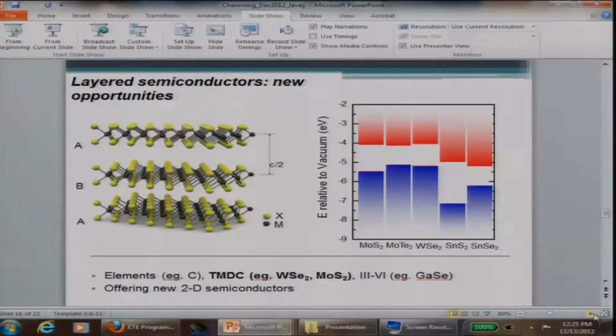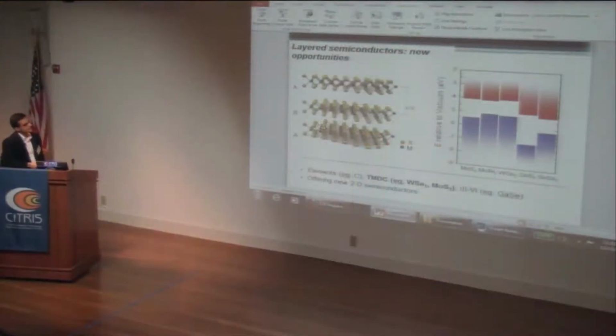To answer that, layered semiconductors present a new area of opportunity for making new types of devices. In the case of layered semiconductors, you have these individual layers that don't have any dangling bonds, they don't have any surface defects, they're fully passivated, they don't oxidize. Within each layer, your bonds are covalent or ionic, and then you have these sheets or layers, and they are stacked on top of each other by van der Waals forces. So you can now start to imagine if you can peel off one of these layers or somehow grow just one of these layers, you will have a single monolayer without any dangling bonds, without any native oxide, and you can start thinking about making devices that are really at the molecular scale, at least in terms of thickness.